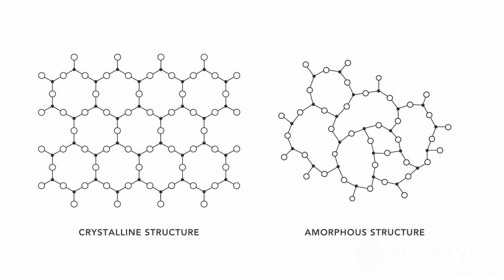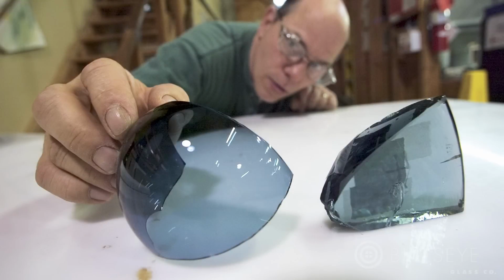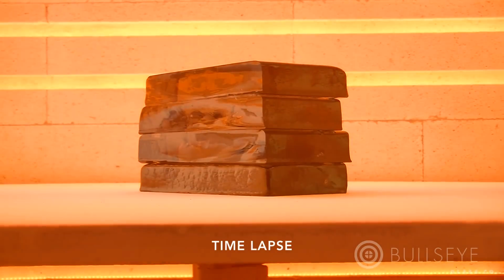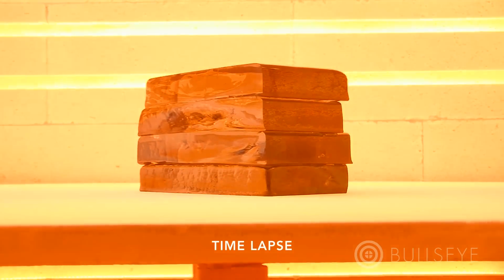Glass is an amorphous material. Its molecules are not arranged in a regular specific pattern, like those of a crystalline material, but are random in their configuration. Because of its amorphous molecular configuration, glass reacts to heat differently than do other materials. Whereas a metal heated to its melting point will change almost instantly from solid to liquid, glass will go through a gradual transformation. It will go from behaving like a solid to behaving like a liquid.